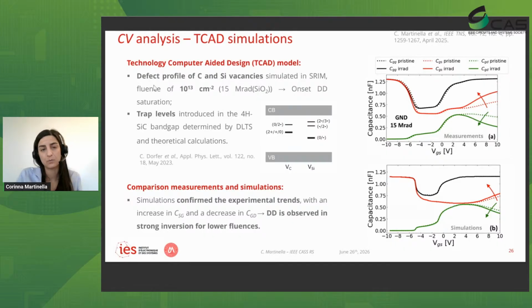And so we simulated that in TCAD by creating a profile of defects of carbon and silicon vacancies in the device. The trap levels were introduced in the band gap of silicon carbide, and they were determined by either theoretical calculations or by the DLTS measurements, which were reported in a previous publication. We can see here the results from our simulation, and we managed to reproduce the onset of displacement damage, and so to confirm the measurement.